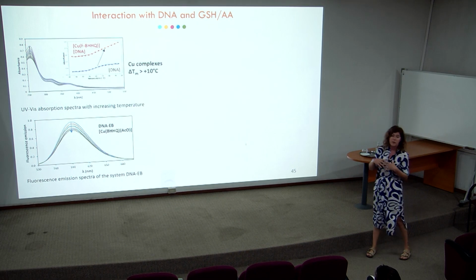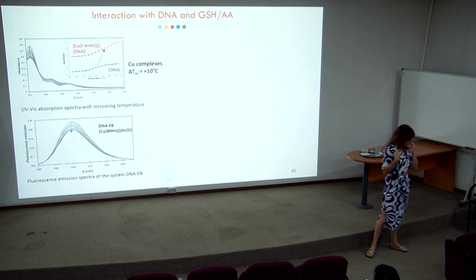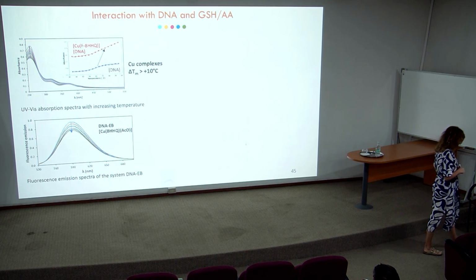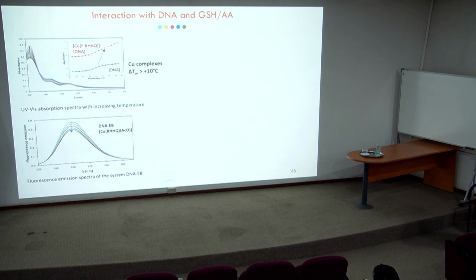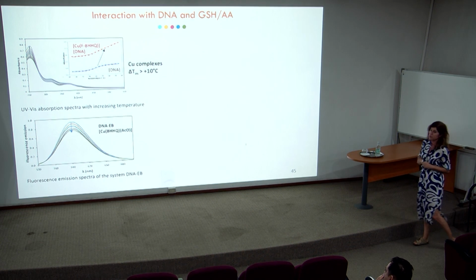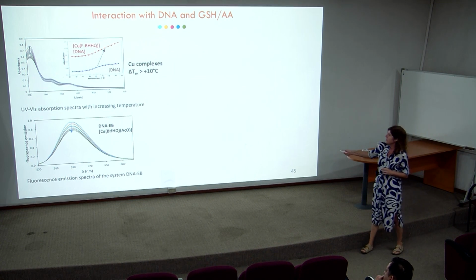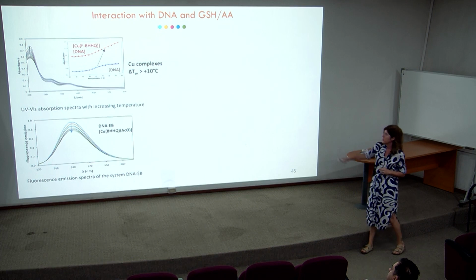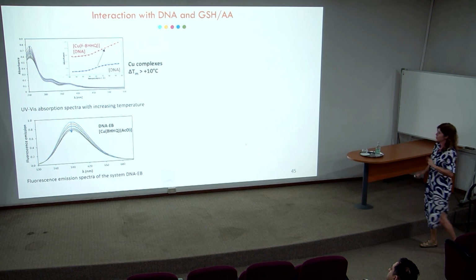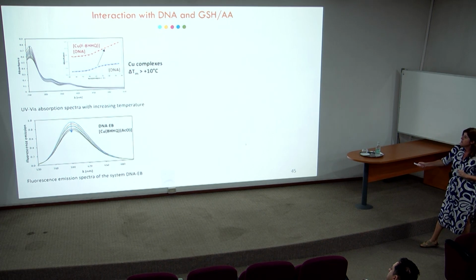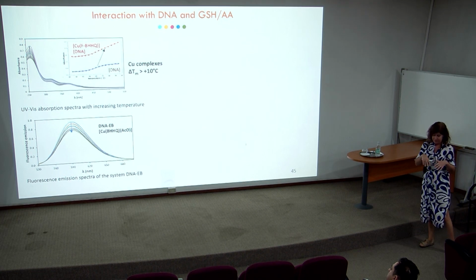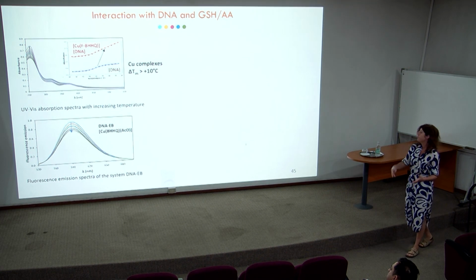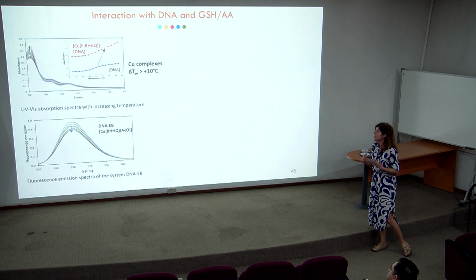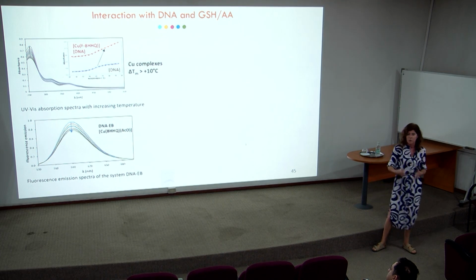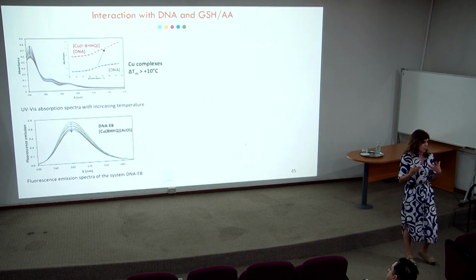DNA might be a target for the compounds. We spoke about this during this week. So we did studies using melting temperature. So this is DNA alone. This is DNA with one of the copper complexes, a mixture of 1:1. And you can see that there is an increase in the melting temperature, which is indicative of a strong interaction between the compounds and DNA.